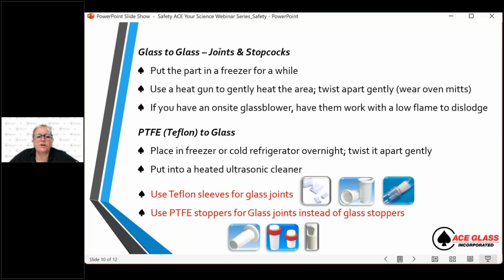Some people prefer to use a heat gun. That is a tricky situation because if you don't constantly move it, you can get a hot spot in it and you can cause the glass to lose its integrity. Also, it's important to point out you should always wear oven mitts to not burn your fingers, right? The glass does get very hot. Ideally, if you have an on-site glass blower, I know some companies and some universities still have one, just bring it to them. They are specialists with that. They can do that super easy and help you get that joint unstuck.